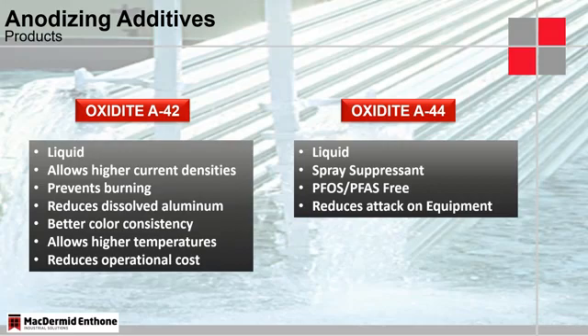It also would allow people to operate at slightly higher temperatures to get the same surface properties as working without some of these additives. So if someone has problems with their cooling equipment, again, this would be a good way of mitigating those issues and problems. And in general, it reduces operational costs from a standpoint that, if we dissolve less aluminum back into the solution, we have to discard less solution. We have much longer intervals before we have to reduce the aluminum concentration of the anodizing bath.